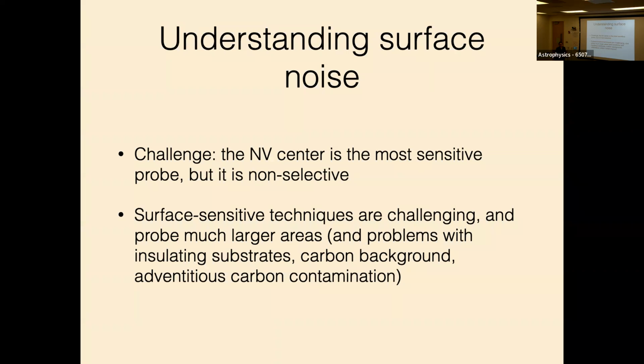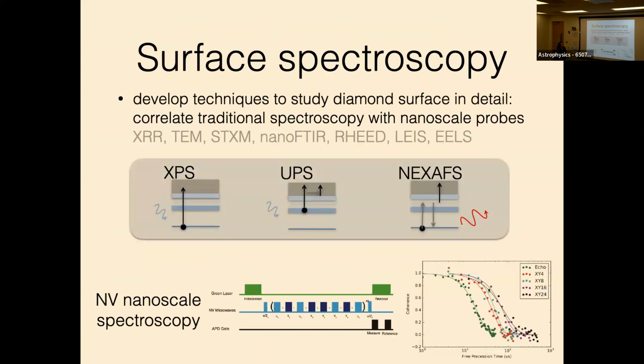And there are a number of other technical problems associated with working with diamonds specifically. So about 6 years ago, my group embarked on a pretty broad project of doing the dumb experimentalist thing, which is to just try every surface spectroscopy technique and see, if we look at this diamond surface in gory detail, can we find anything that is correlated with the quantum measurements that we can make on single NV centers. So you get this alphabet soup of a large number of electron-based techniques, X-ray-based techniques, scanning techniques, and we zeroed in on X-ray photoelectron spectroscopy, ultraviolet photoelectron spectroscopy, and near-edge X-ray absorption fine structure as being the key tools that actually ended up being helpful.